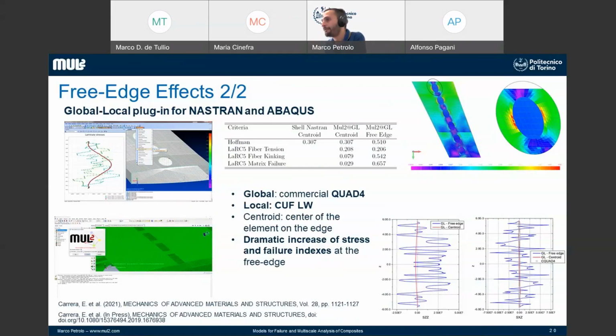In this plot, we have the stress components. The red one was taken just before the free edge. The blue one is just at the free edge. So as you can see, you move a few millimeters and there is a huge jump in the modulus of the stress state. So this means that in that area, you can have a very high stress field and failure may occur.